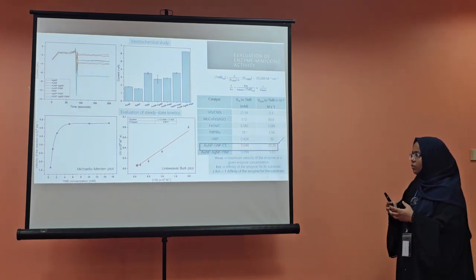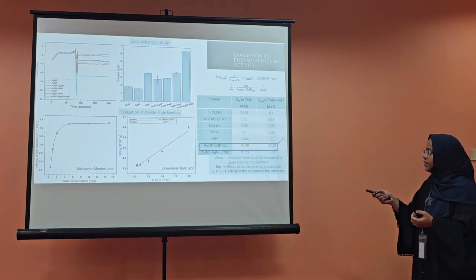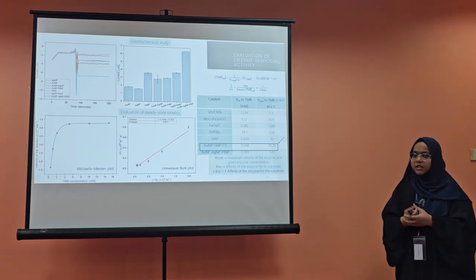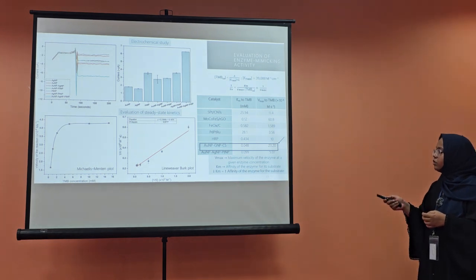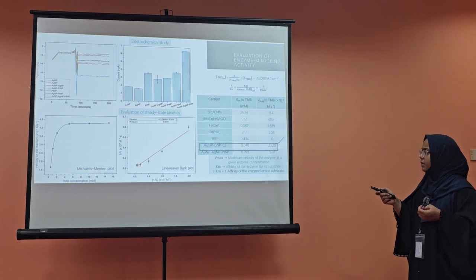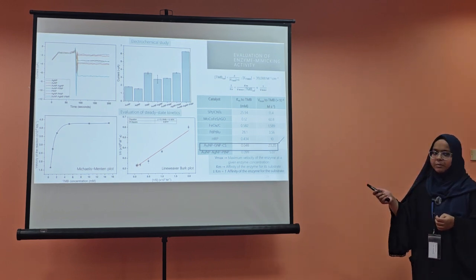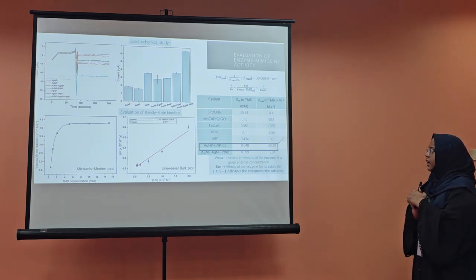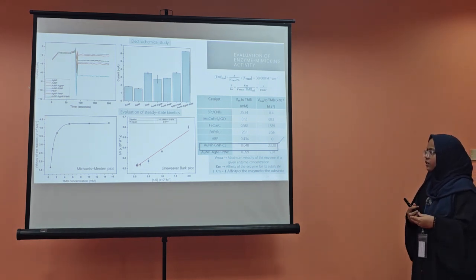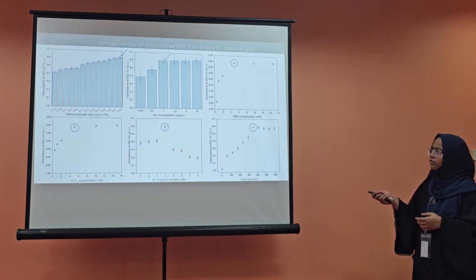Steady state kinetics was also assessed, and Km and Vmax values were calculated. As you can see, the Km value was very small. The Michaelis-Menten constant was almost 5 times lower than that of HRP, which confirms that this proposed trimetallic nanocomposite is highly active, and it has good enzyme mimicking properties, and was used in further experiments.